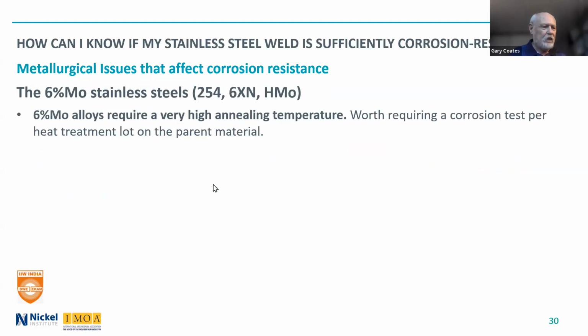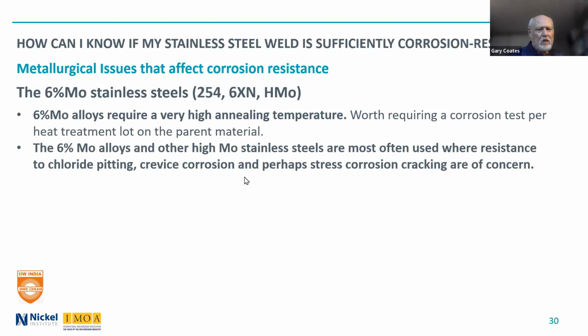Let's move on to 6 moly stainless steels. I've got about 10 minutes left here. 6% moly alloys require a very high annealing temperature, and this is where a lot of mills that make this alloy go wrong. To get rid of all the intermetallic phases that are present after hot rolling and that sort of thing, you have to anneal them at a very high temperature. And so we recommend that you do a corrosion test per heat treatment lot on the parent material, because if the parent material isn't good, the welder is only going to make it worse. There's nothing he can do about that.